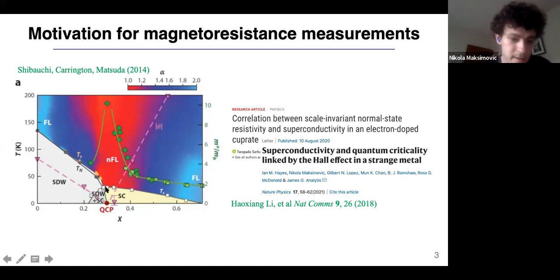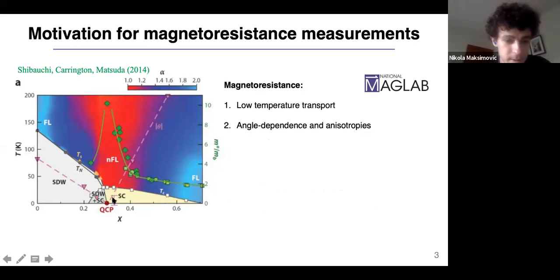The issue is that much of the data in this most interesting regime is only available above 30 Kelvin, above TC. And generically, you start to see phonons come in at those temperatures, and it becomes very hard to separate out what is an anomalous source of scattering and what is a more conventional source of scattering. So the low temperature data is extremely useful for a transport measurement. And this is where magnetoresistance comes in. One way to get data at low temperature is to just put the sample in a giant magnetic field, and you can get a resistive signal once you kill superconductivity. There's an added bonus: using magnetoresistance, you can to some extent evaluate anisotropies in the scattering rate or Fermi surface. But most of these goals are contingent on having at least a base level understanding of the mechanism for magnetoresistance. And that's proven fairly difficult.